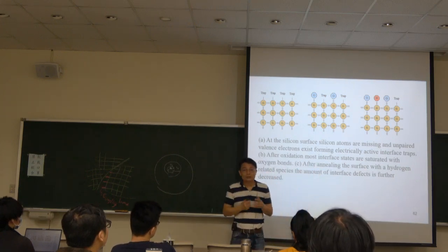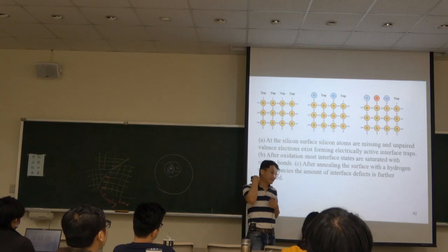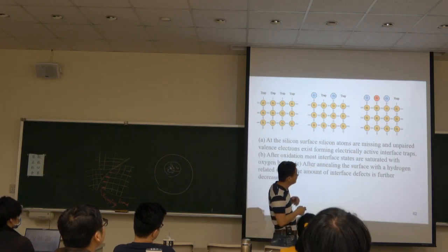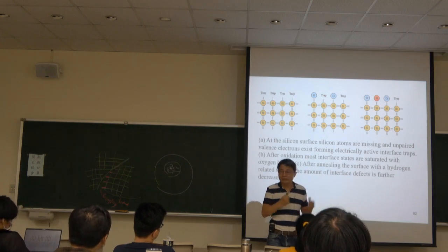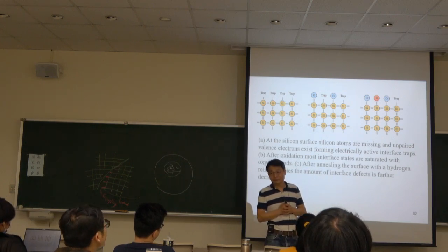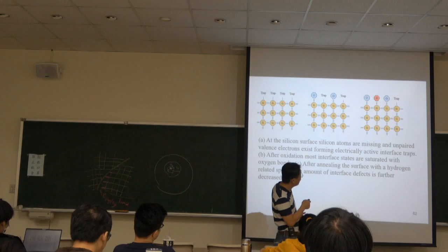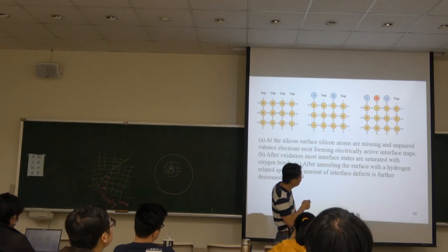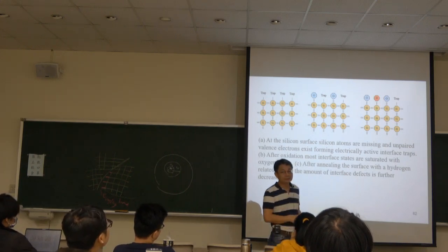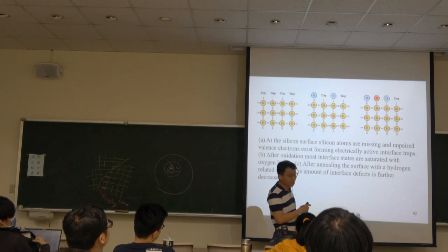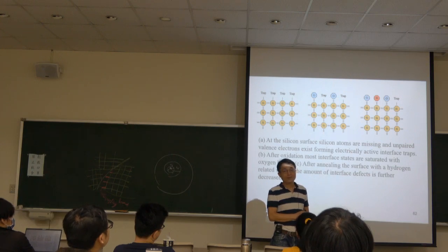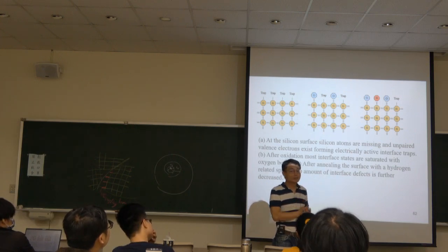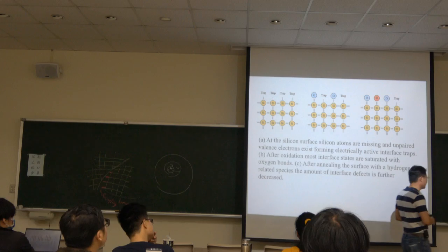That is a weakness: once it is shone by light radiation, like UV light, the UV could cut the bonding between silicon and hydrogen. So the hydrogen will disappear again, and therefore form the dangling bond again. Do you understand?